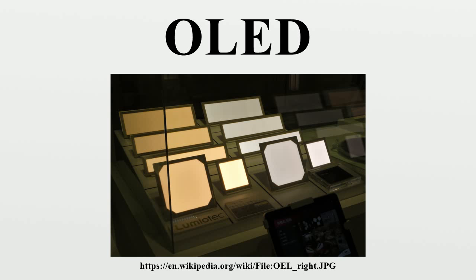Applications of OLEDs in solid-state lighting require the achievement of high brightness with good CIE coordinates. The use of macromolecular species like polyhedral oligomeric silsesquioxanes in conjunction with the use of phosphorescent species such as Ir for printed OLEDs have exhibited brightnesses as high as 10,000 candelas per square meter.